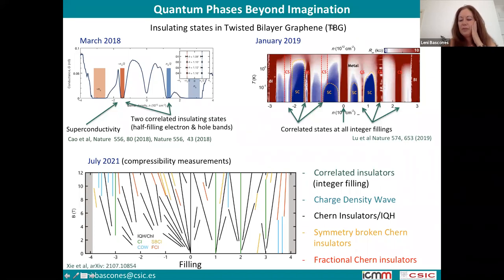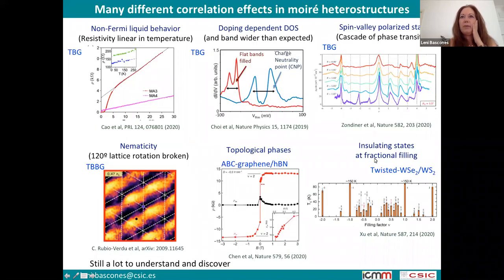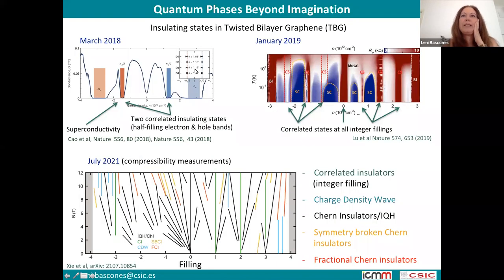This is for TBG. In particular, these are different types of systems, but some of these properties have been observed in several systems. So here, it was observed that superconductivity was present in a much larger region of the phase space. There were several correlated states at all the integer fillings. As of last month, these are the insulating states which appear in a single sample from compressibility measurements as a function of the filling and the magnetic field. So all these lines are where they can detect insulators, and in fact, there are different kinds of insulators.